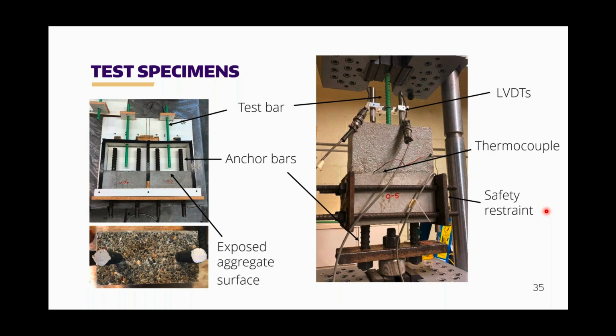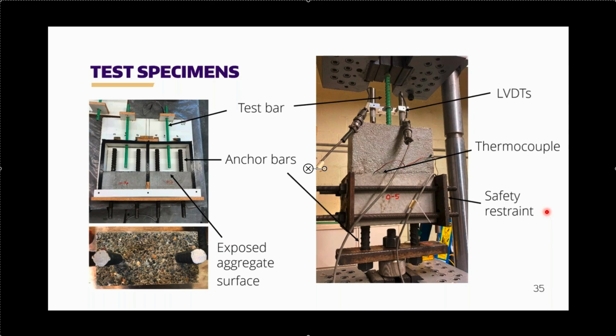tension. The main thing that we collected, that main data point, is the displacement of the epoxy bar in comparison to the top surface of the polymer concrete. We also recorded the load from the machine itself. There is a thermocouple embedded in the specimen that allowed us to track the temperature not only while testing, but also while curing. I'm going to pass it back over to Travis, and he's going to go a bit into the experimental results.